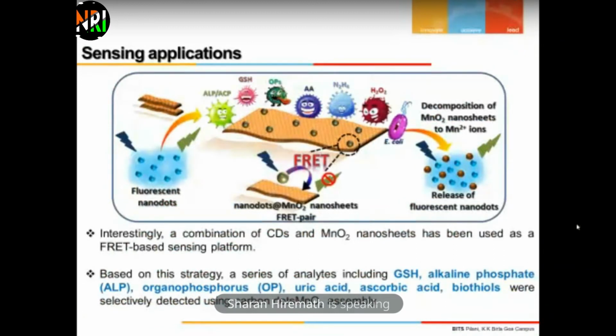Now if we come to the sensing part of these carbon dots, along with carbon dots, here we are using MnO2 nanosheets, manganese dioxide nanosheets. If we talk about MnO2 nanosheets, they are two-dimensional structures with high environmental compatibility, and they are high surface area. And these MnO2 structures come with different forms like nanosheets, square plates, nanorods, nanotubes. But here our interest is with nanosheets because they provide large surface area. Because of their large surface area, they can be highly used as nano quenchers, and nano absorbents, and are also used as catalyst.